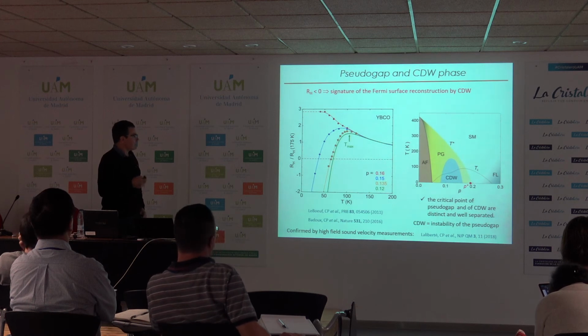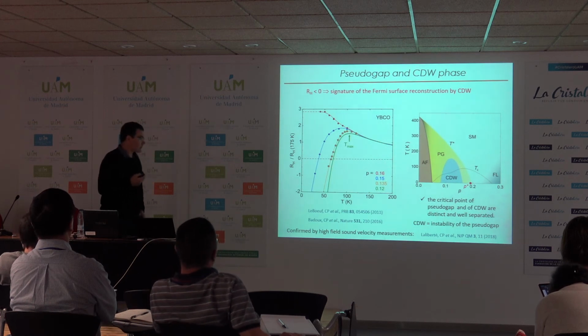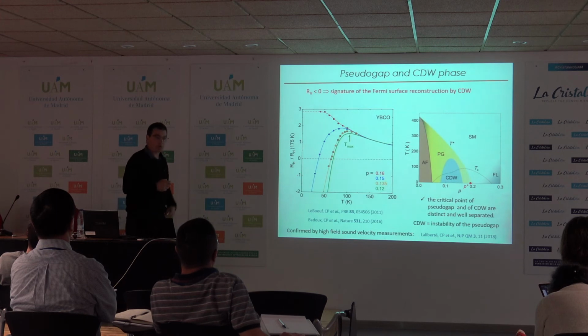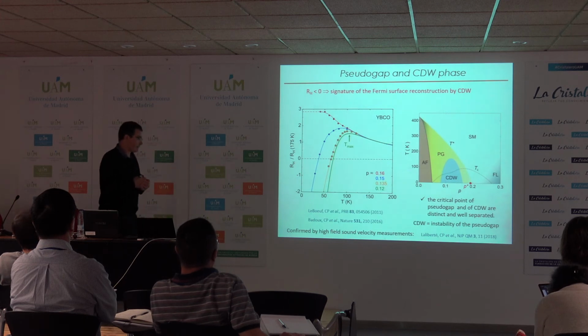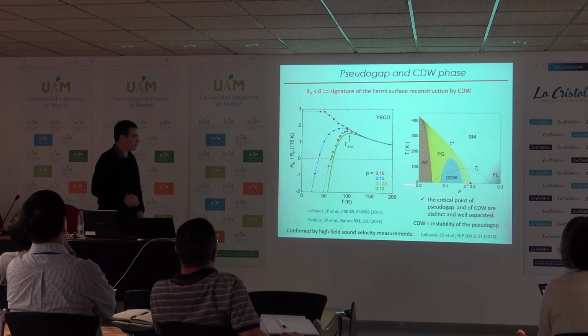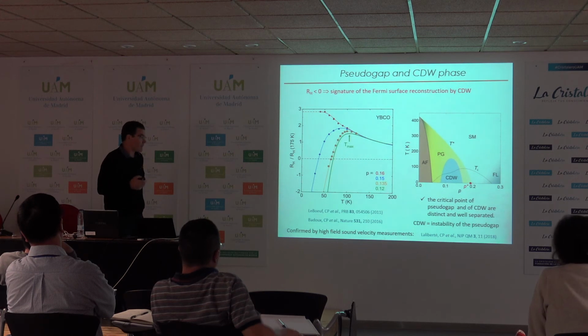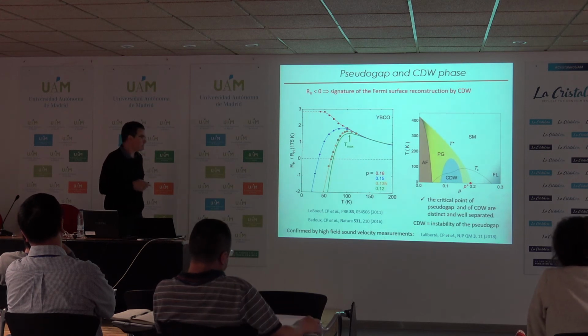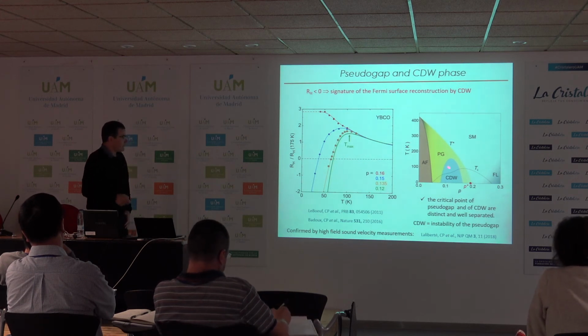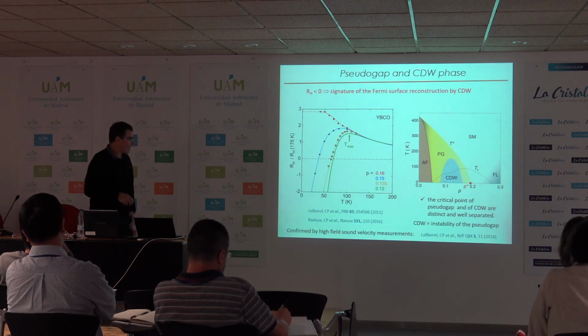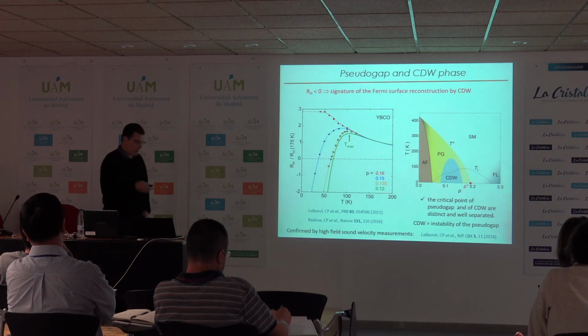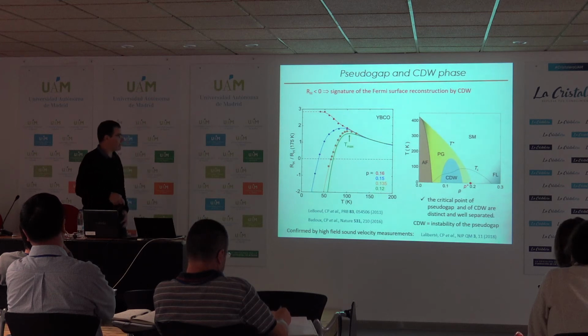And what we have inferred from this measurement is that the critical point of the pseudo-gap and of the charge density wave are distant. And it seems from this measurement, and as we have drawn this diagram, that the charge density wave is in fact an instability of the pseudo-gap. And the critical point of the charge density wave has also been confirmed by high-field sound velocity measurements that we have performed with my colleague David Leboeuf in this paper.